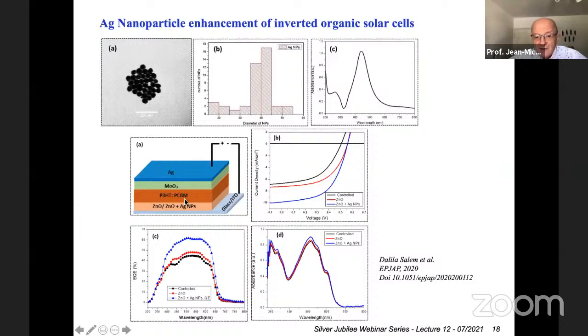And then we have a photovoltaic absorber, which is a polymer composition, which is a very classical polymer composition, nothing very original there. And we have a hole collecting layer, not very original also, and a silver anode on top, which will collect the plus charge. That inverted structure was designed to increase the stability of the solar cells, and I will not develop too much. These nanoparticles were developed by a solvent method, by a solvent reduction of silver ions, a very classical technique.